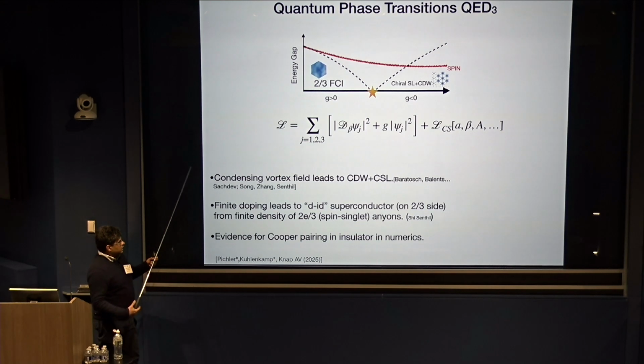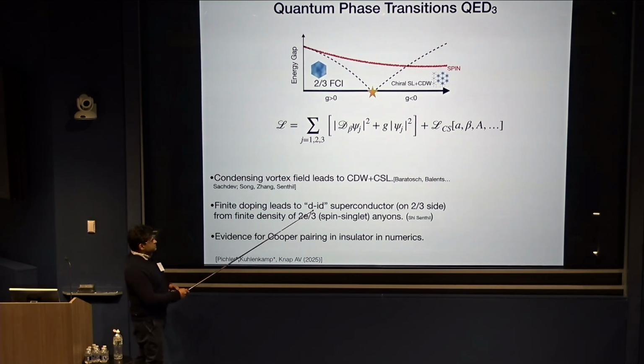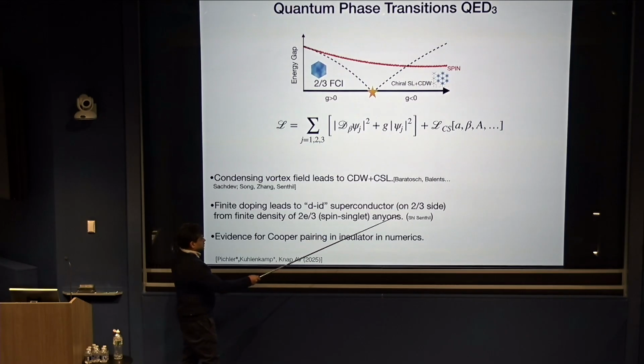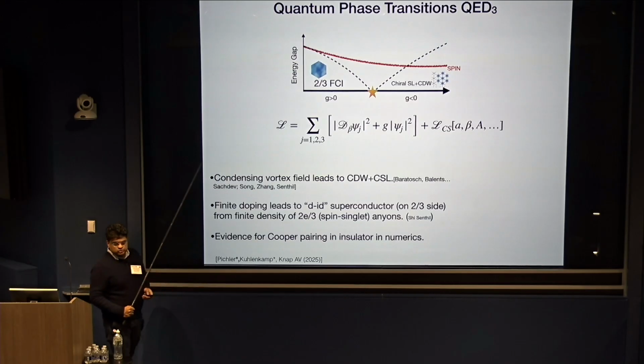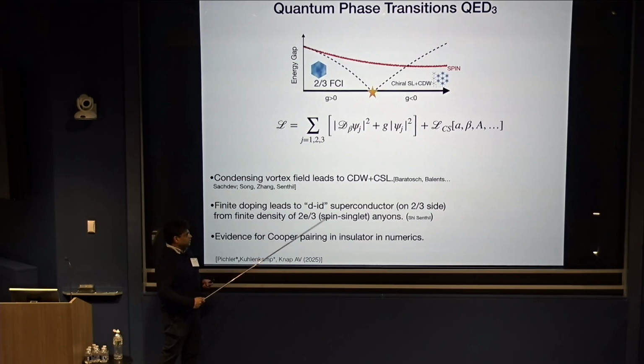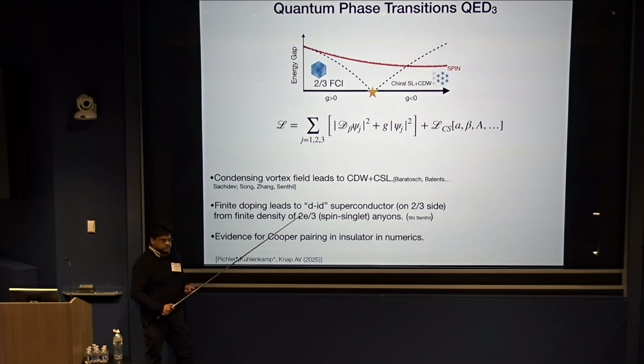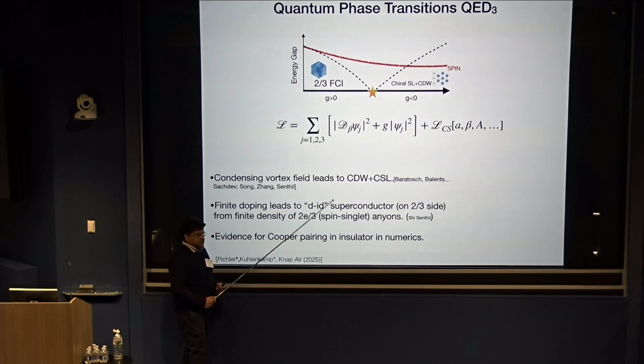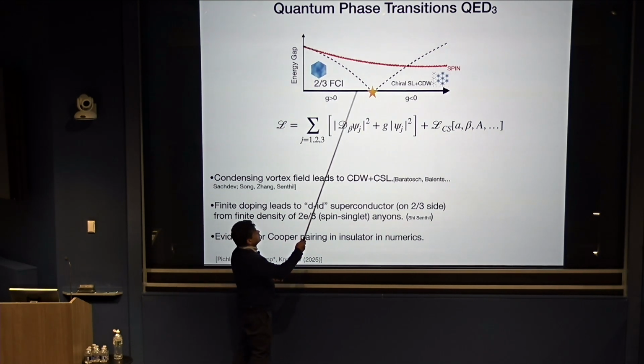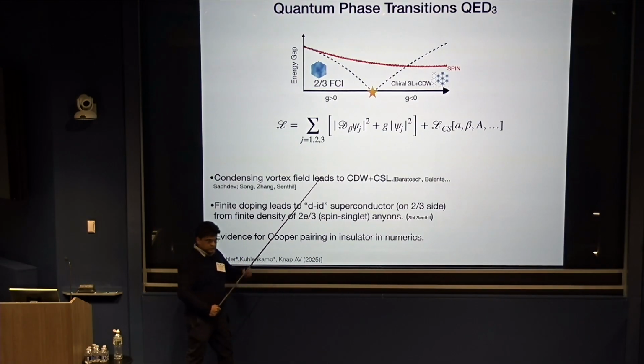In this particular case, the superconductor you get is d minus id, and you can again argue that on the 2/3 side by a finite density of these 2/3 charged anyons. Okay, and it's important that they are 2/3 charged. The dynamics of this model automatically singles out these as the lowest energy anyons. Usually, if you had a 2/3 state in fractional quantum Hall, you would have got the e/3 anyon. That was low energy. You wouldn't get this particular type of phase diagram. But having the two-thirds state in proximity to this chiral spin liquid plus CDW lowers the energy of this two-thirds anyon, not the minimally charged anyon. It's a spin singlet. That's why it's preferred.